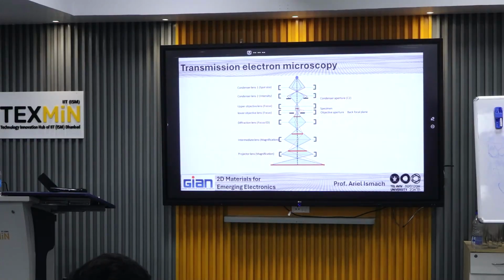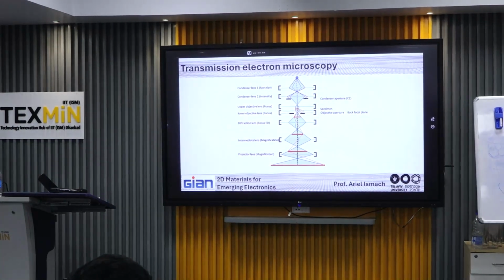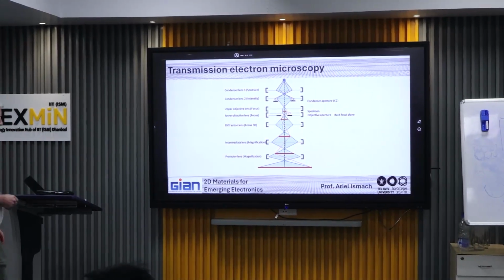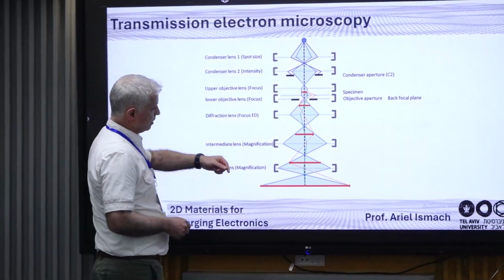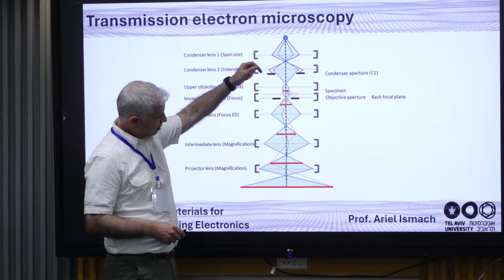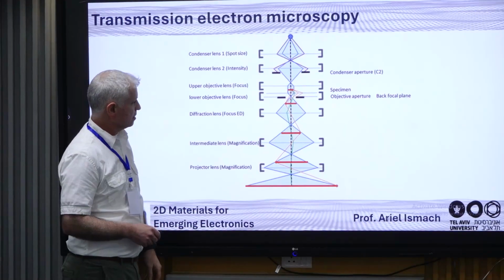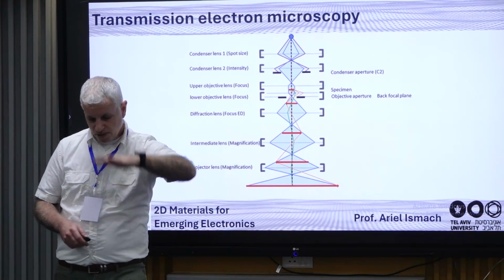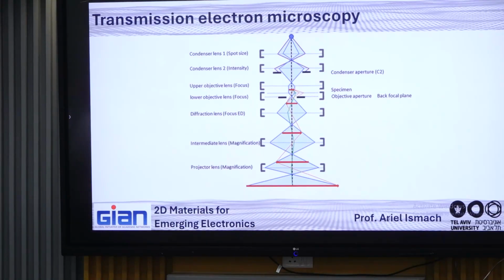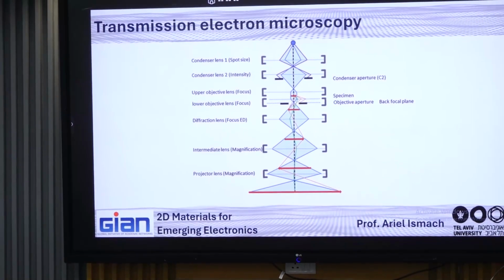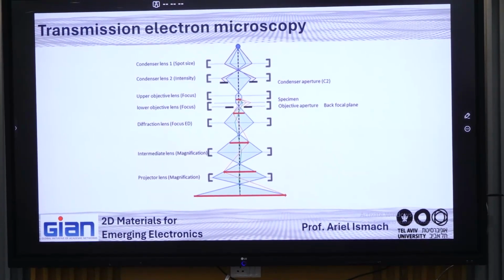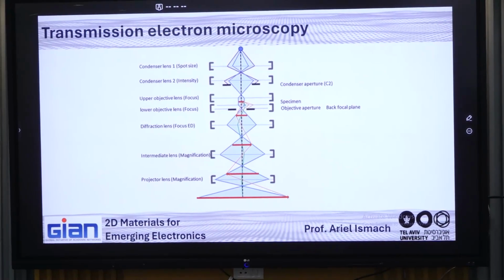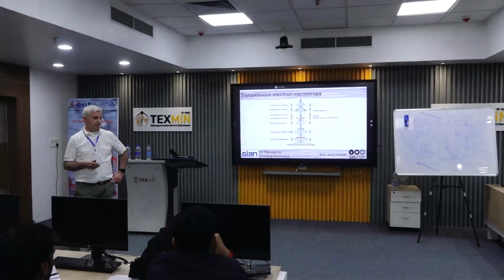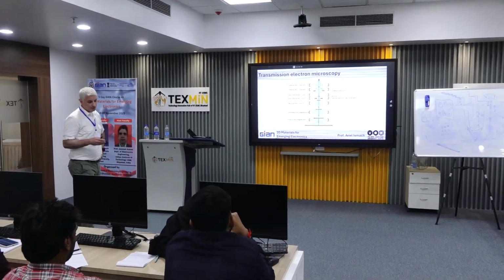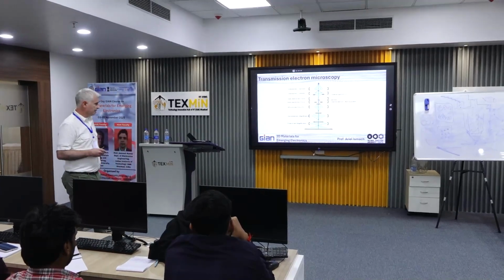Okay, and then the other option is, of course, the transmission electron microscope. In transmission electron microscope, instead of hitting with the electron beam, you now need to transmit the electrons to the other side. So here's the specimen. The specimen will vary depending on the method that you're using, but you transmit the electrons through the specimen, and therefore there are some critical issues with the specimen. You cannot put any sample, right? You need to put a sample that is thinner than 100 nanometers. And if you want atomic resolution, it must be much thinner than that.